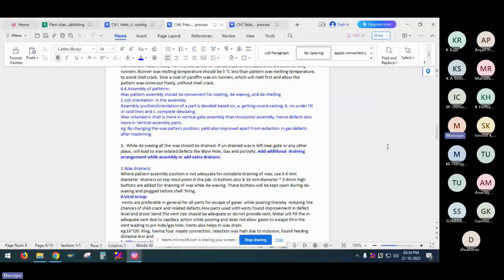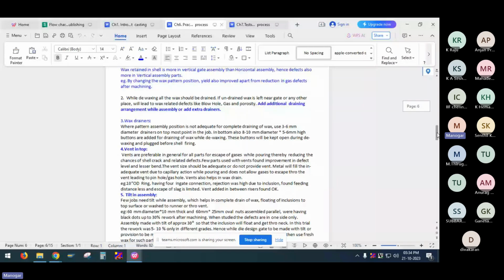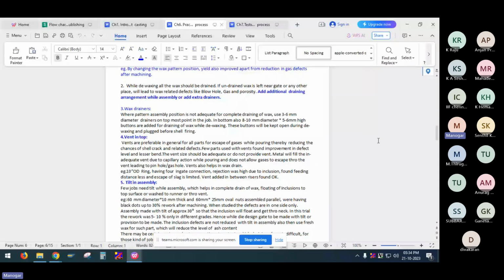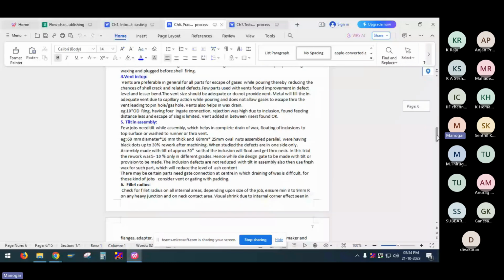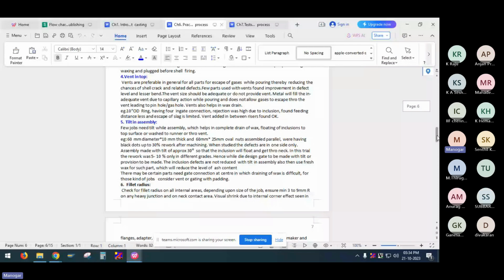So at this point we have only covered draining, the wax drainers. Apart from the wax drainers, we should also have a vent at the topmost point, for the gases to come out, and it also acts as a wax drainer, where no drainers are kept based on the simple shape or size of the casting. The tilt assembly we discussed for a sound casting. The assembly position is decided whether horizontal, vertical or tilt. In some of the castings we have better yield and quality by doing a tilt assembly. Some of the defects are eliminated when you do a tilted assembly.